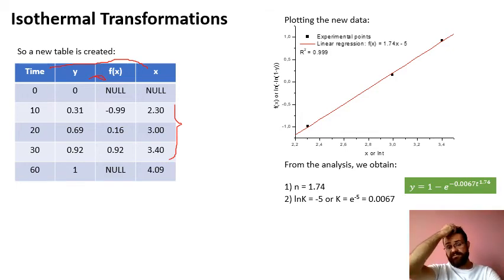This experiment is good because it's very simple and we can use it for other metals, for example copper or aluminum or steel, and we can follow this process by simply having the transformed fraction related to hardness. Then maybe we can even work with more data points to get a more precise estimation of the JMAK equation coefficients.